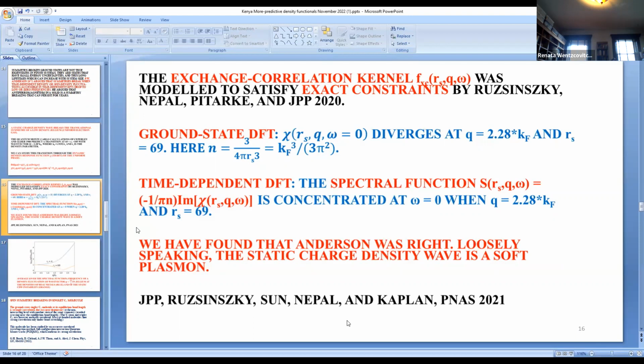We also looked at this from the point of view of time-dependent density functional theory, in which we construct chi of RS, Q, and omega, and from it the spectral function S of RS, Q, and omega, which is minus 1 over pi times the density times the imaginary part of chi. We found that quantity is concentrated at zero frequency when the wave vector and density are both critical. I'll show you what sense that's true.